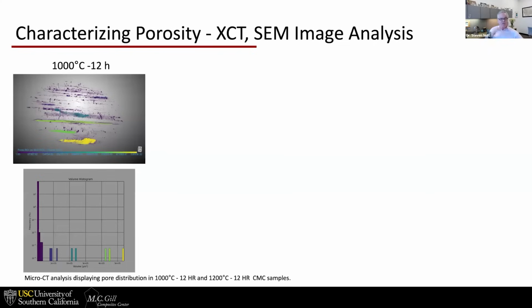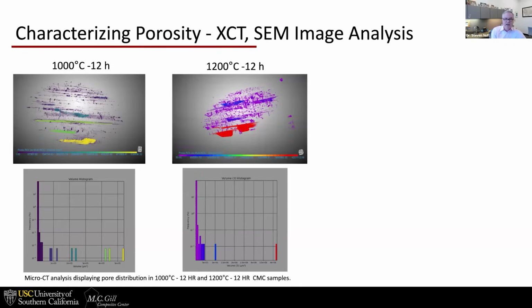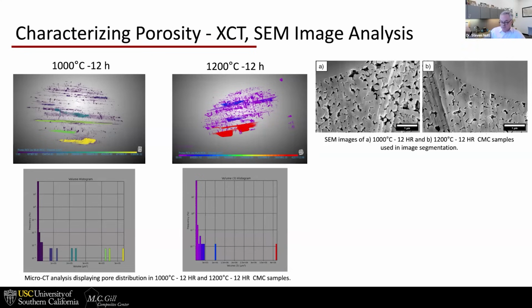We can begin to understand the three-dimensional nature of the pores by volumetric imaging, X-ray CT, and what you see on the left here is images of pores. Pore volume is color-coded, so yellow is larger volume than green, which is larger volume than purple. And then on the bottom is frequency on the vertical axis and volume on the horizontal axis. And you can see that one pore might actually account for a fairly large fraction of the overall porosity if it's sufficiently large. This is a higher sintering temperature, same sintering time. You can see the pore sizes and pore shapes. They tend to be quite elongated along the fiber directions, which is not too surprising.